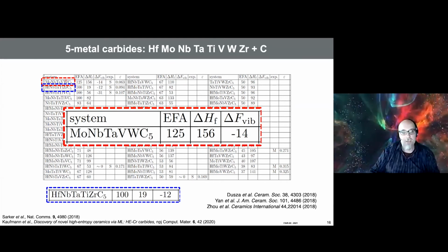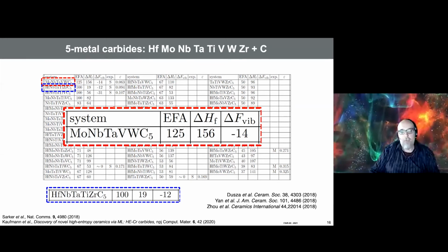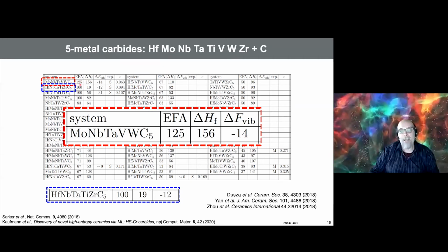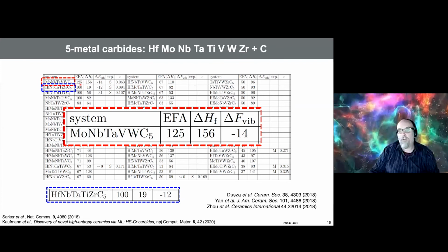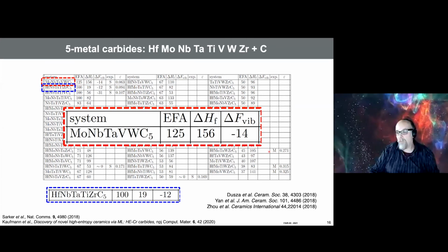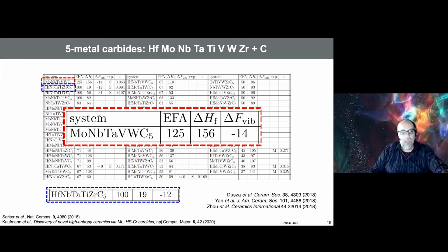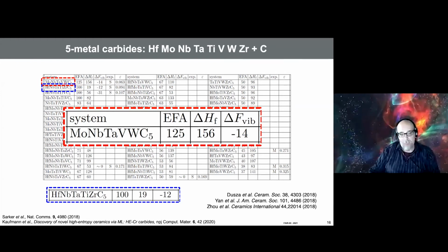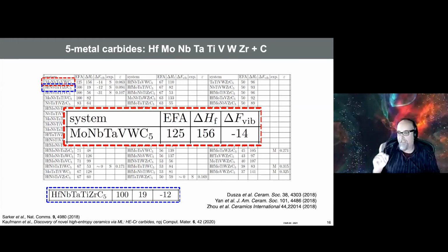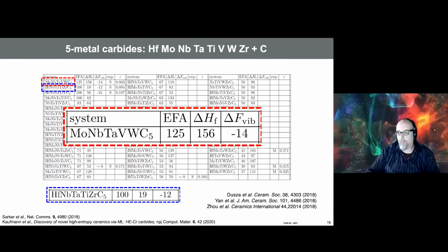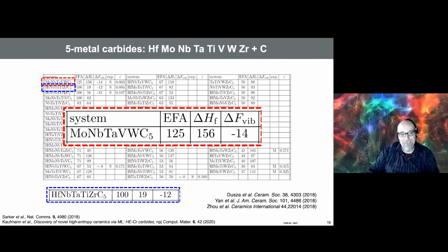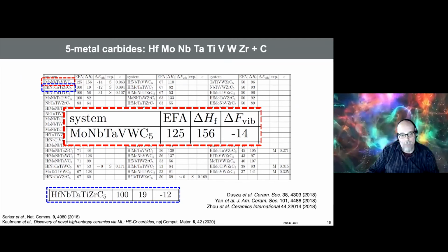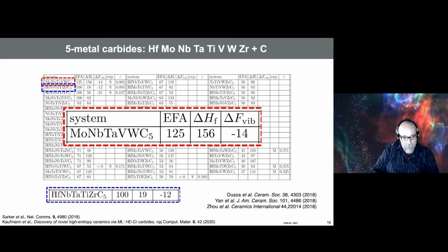They do the experiments, and they discover that the one with high entropy forming ability actually does form a solid solution, and the one with low entropy forming ability does not. Okay, so this is already a success, but the biggest success of big data, and it's good for all our community, comes from the analysis of the first two. Look carefully at the first two. Let's start from the second one.